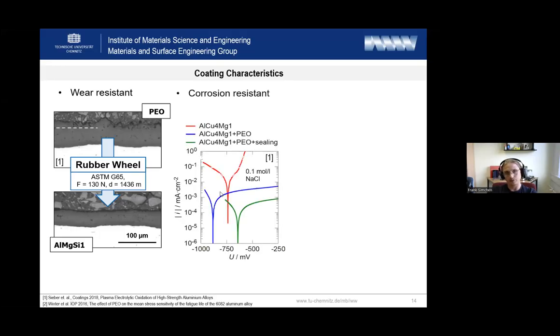And if we speak about the corrosion resistance of such PEO coatings, they offer good corrosion protection, but especially when you are dealing with aqueous or liquid corrosive media, it's recommended to apply an additional sealing step. And this is related to the morphology of the coatings. Of course, this crystalline aluminum oxide itself is very resistant against chemical attack, but we have to deal with the intrinsic crack structure. So if you place this component for a longer time into any aqueous media, it's possible that the corrosive components can come through the micro crack network until the substrate.